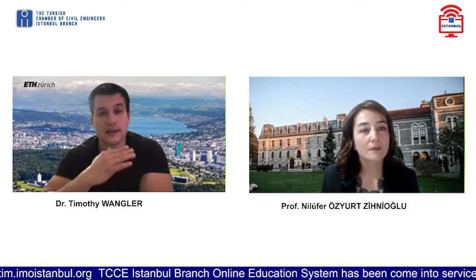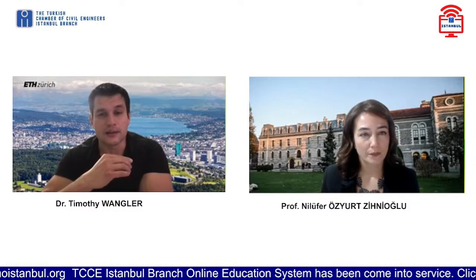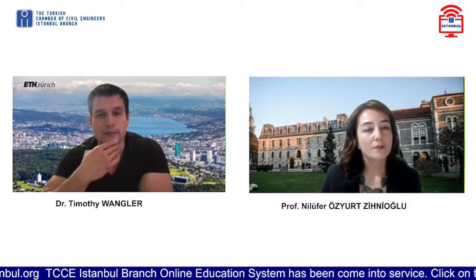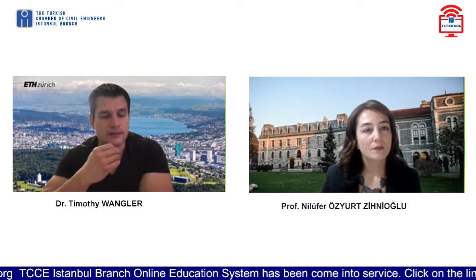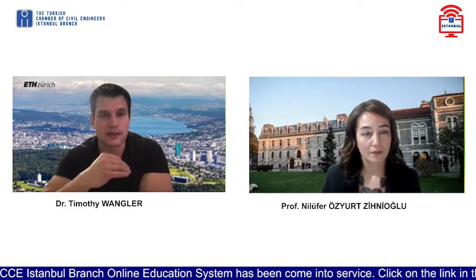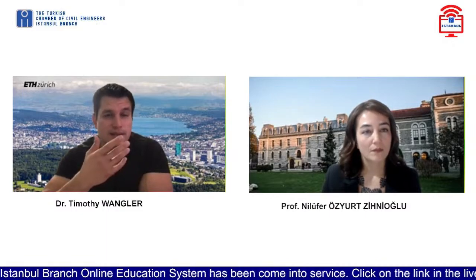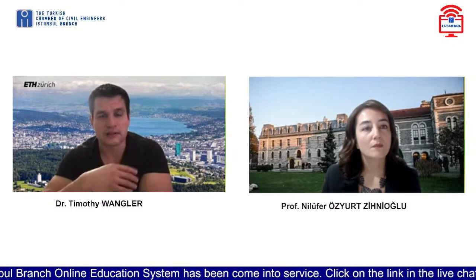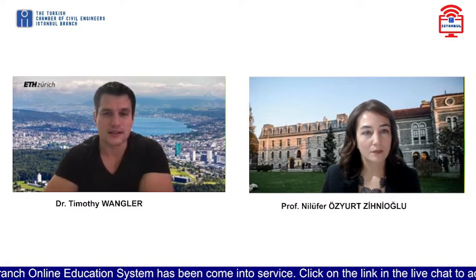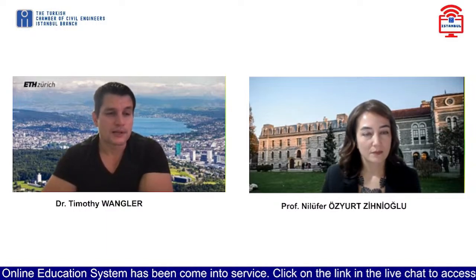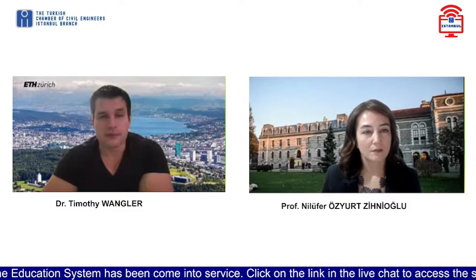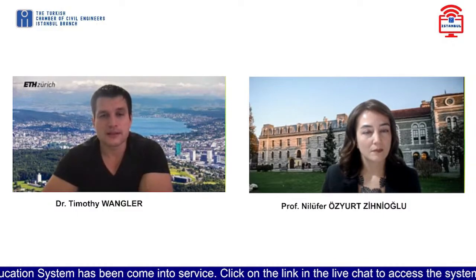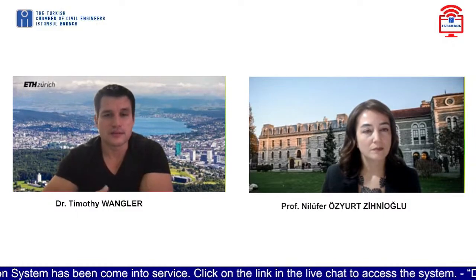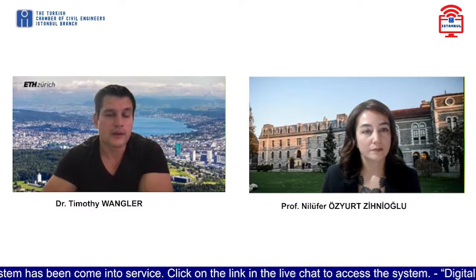In our case, we see that they carbonate very fast, much faster than the bulk concrete. And this is, of course, bad for standard concretes, especially if you're trying to use it as a concrete cover. But if you are in a prefabrication setting, then maybe it's something that you can take advantage of to speed up the process of carbonation.